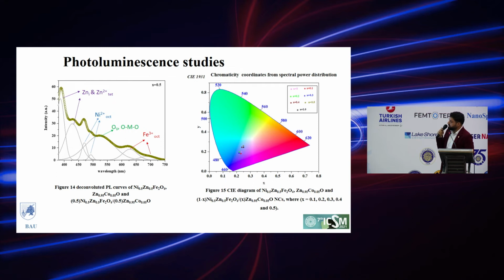Again, the chromaticity coordinates were determined from the spectral power distribution of all samples. And the color coordinates showed a shift from the blue region to the violet region, and this is favorable for photocatalytic applications because it means that there is a possibility of harvesting a larger amount of the visible spectrum.